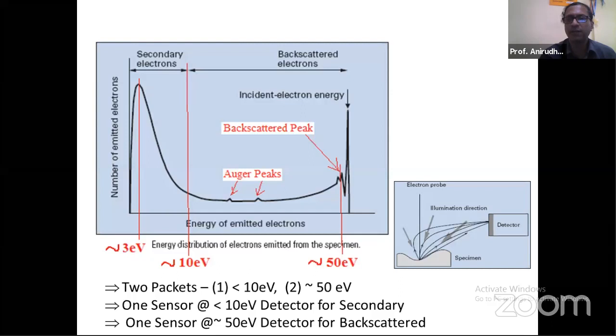It shows a distribution, but then we should know that there are two different packets. One packet, which is on the left, is of low energy values, whose magnitude is close to 3 electron volts. And the other one, which is on the right, is of the order of 50 electron volts. So basically, there are two different packets. Of course, they are not two discrete packets, but mostly we can say that they belong to two different classes. One is centered around 3 electron volts, which is low energy, as compared to the other packet, which is at a high energy and has a value of nearly about 50 electron volts.